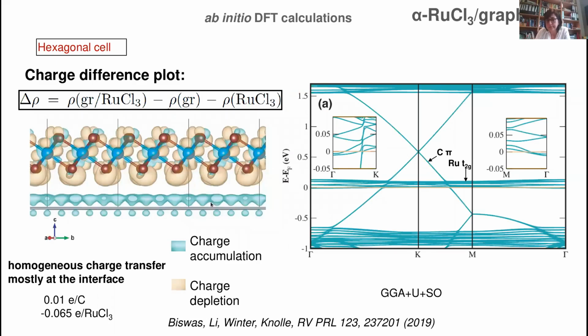First of all, what we observe is that there is a strong charge transfer between your graphene layer and your alpha-ruthenium trichloride layer. So you can see it here in the band structure: pristine graphene would have the Fermi level here. Graphene gives electrons, so it gets hole doped when you put alpha-ruthenium trichloride on top of it.